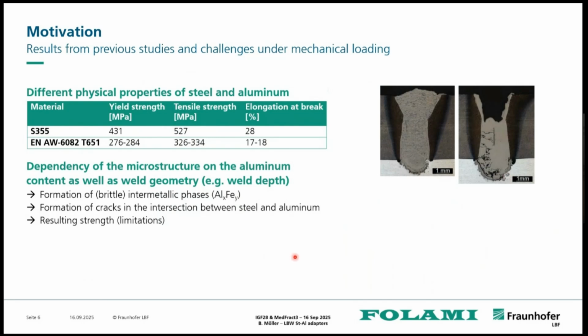So this usually leads, when joining by welding, to the formation of intermetallic phases. Some of them are quite brittle, so they lead to cracks and are critical for fatigue failure. And then we also have some cracks in the intersection between steel and aluminum. We see it here, which is not a perfect joining between these two materials. Then you already get cracks inside it, while if there is a more or less good joining process, you can avoid most of the cracks and also most of the brittle intermetallic phases. However, resulting strength limitations might occur.